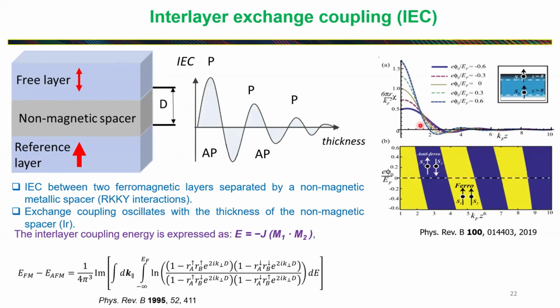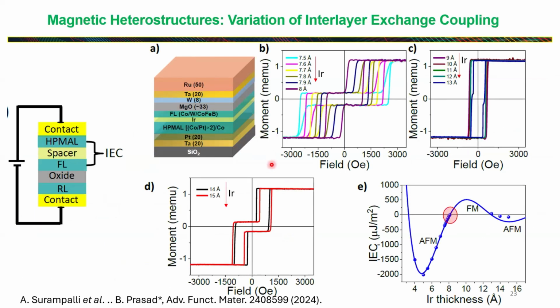So if you somehow modify the electronic states at the interface or at the Fermi level, then you can go from parallel to the anti-parallel configuration between these two layers. And this is exactly what we have done. So we put the iridium as a spacer layer between the two ferromagnetic layers, and then we systematically vary the thickness from 7.5 angstrom all the way to 15 angstrom. We get nice RKKY kind of oscillation, and then we basically optimize the thickness of the iridium, which is close to where you can go easily from anti-ferromagnetic to ferromagnetic coupling.